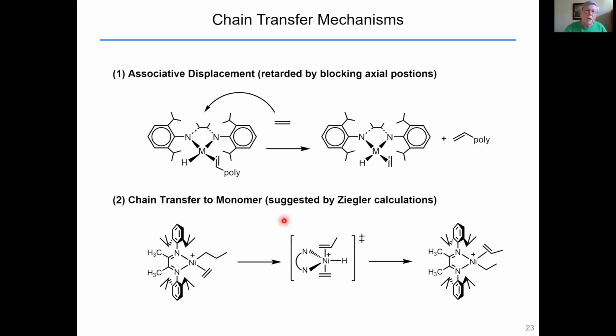associative displacement. Now, Ziegler has suggested that chain transfer may come from the olefin alkyl species in a process called chain transfer to monomer, where hydrogen shifts to the unsaturated species, in this case ethylene, to generate a bis-olefin hydride complex, and that by bulking up the axial sites, this barrier goes up substantially. That may well be true, but of course, even if we do that transfer, in this case, we still have to displace olefin. So this is going to, again, require an associative displacement.